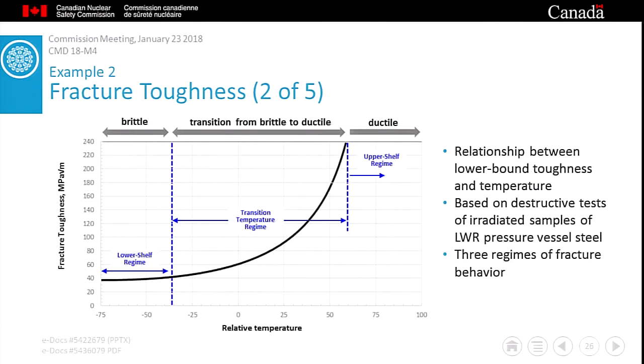Fracture toughness is a property shared by most structural materials. For example, the steel used in the vessels of light water reactors, or LWR. This figure illustrates the changes in toughness that occur as the temperature of a vessel increases from shutdown through to normal operating conditions. Initially, the material exhibits brittle fracture behavior. In this lower shelf regime, should a crack exist, it would quickly propagate without any increase in pressure being required. As the temperature rises, the material toughness increases dramatically, and the fracture behavior transitions from brittle to ductile.